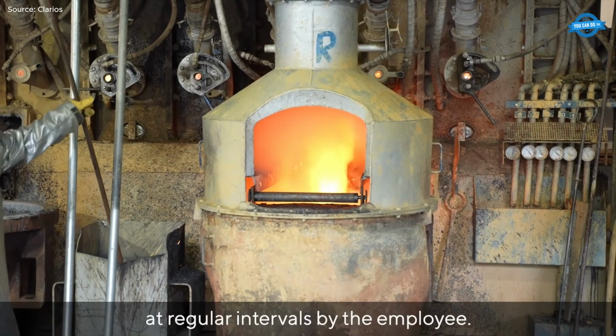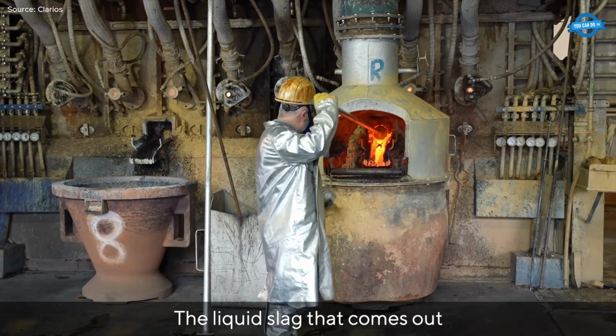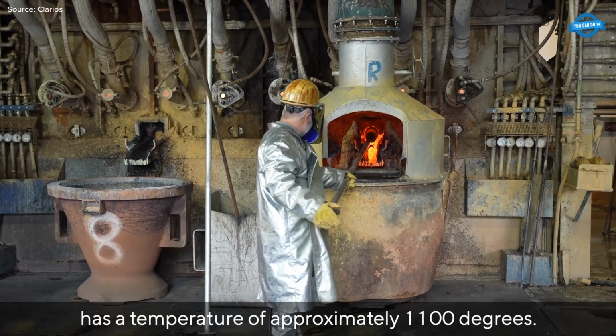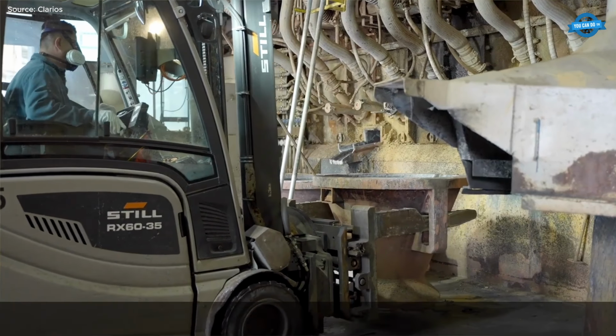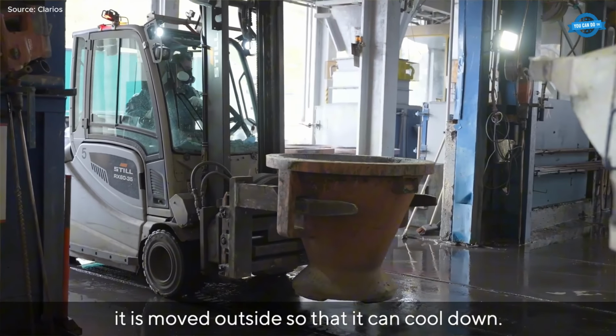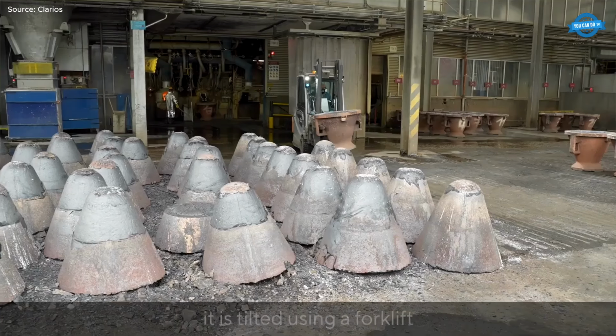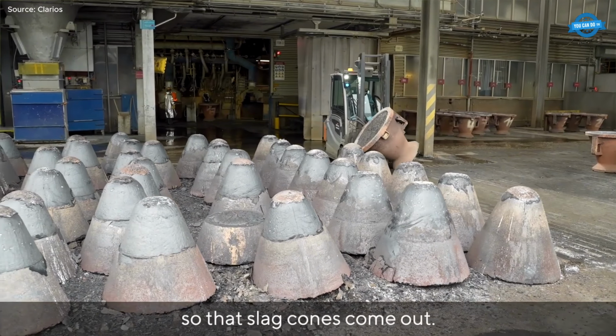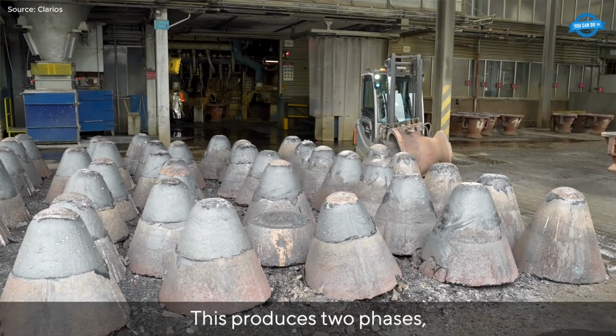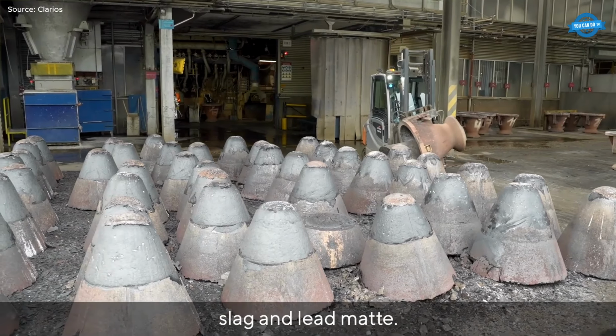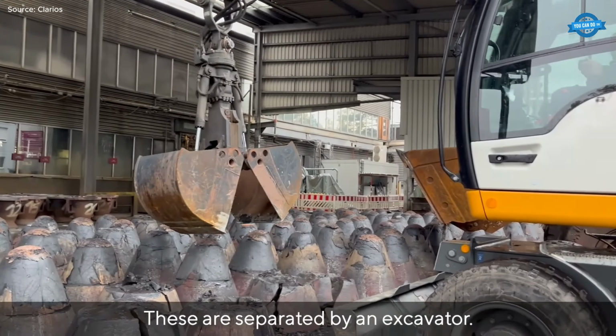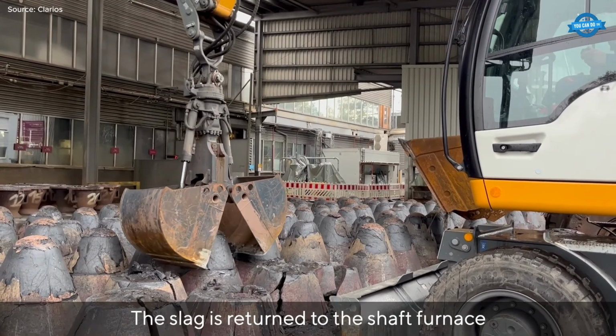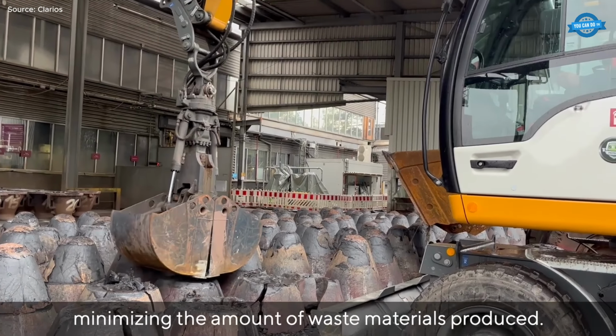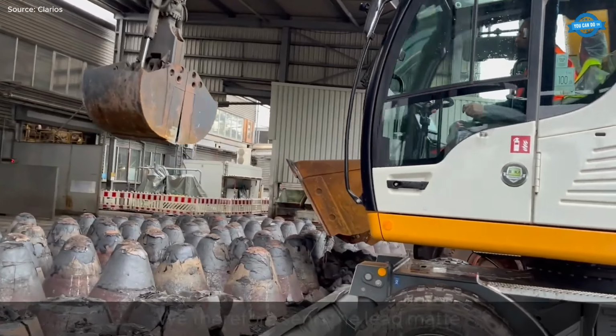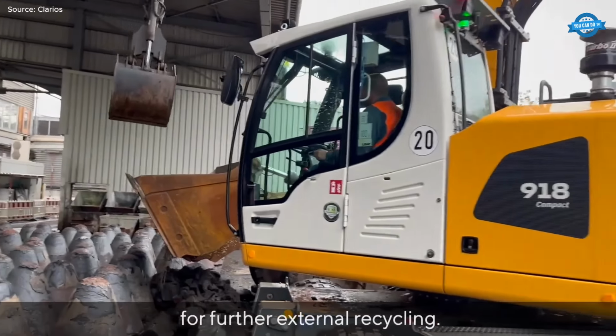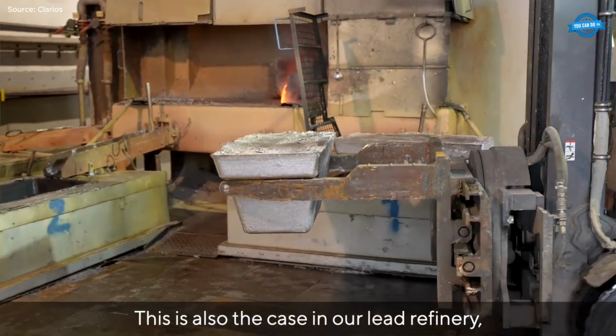The shaft furnace, running 24/7 at about 1,000 degrees Celsius, melts the feed mixture to generate high-purity work lead. A continuous front tap delivers molten lead at around 900 degrees Celsius with 98% purity, while slag is periodically tapped on the side, cooled, and mechanically separated into recyclable fractions. Slag portions are reintroduced into the furnace, while sulfur-bearing leadstone is shipped to specialized refiners. Furnace off-gas passes through thermal afterburning and large dust collection filters before clean emissions exit a 100-meter stack.